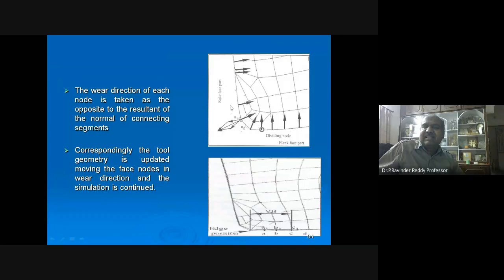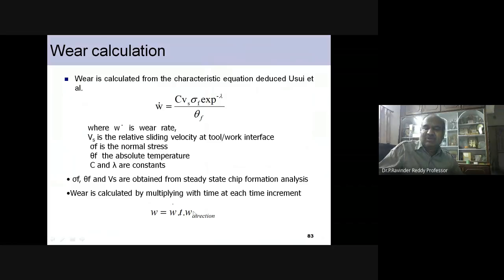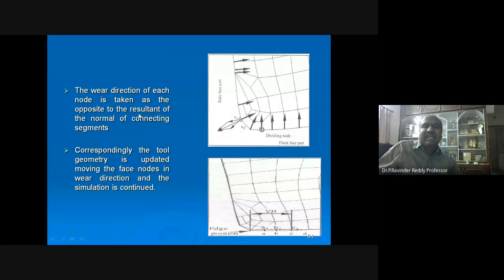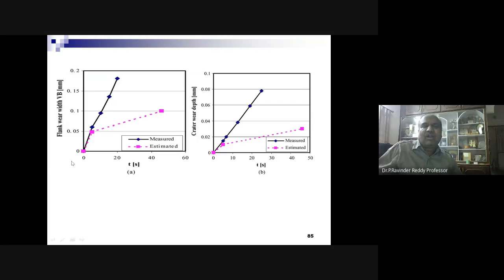These are the phases where the nodes are identified, and the normal to that, when you couple to the previous, they are going to correspond to the wear direction, which we can take from those nodes. The wear direction of each node is taken as the opposite to the resultant of the normals of connecting segments. Corresponding to that, the tool geometry is updated, moving the face nodes in wear direction, and the simulation is continued. And we can plot the flank wear width measured and estimated, and here also crater wear depth against the time. So we can calculate the rate of that and we can showcase.